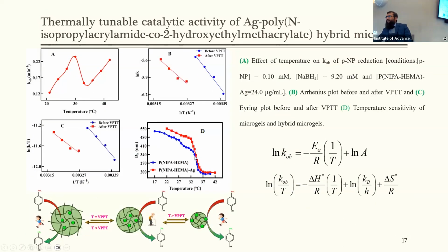Another interesting feature of the catalytic activity of hybrid microgel is the tunable catalytic activity. We measured the value of the rate constant for reduction of 4-nitrophenol at various temperatures in aqueous medium, and the rate constant was plotted as a function of temperature. The rate constant was found to increase initially, then decrease, and then start to increase again with increasing temperature. This sudden decrease in the rate constant is actually associated with the volume phase transition temperature of the microgel system.